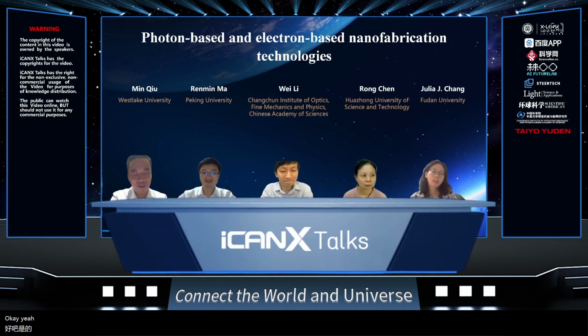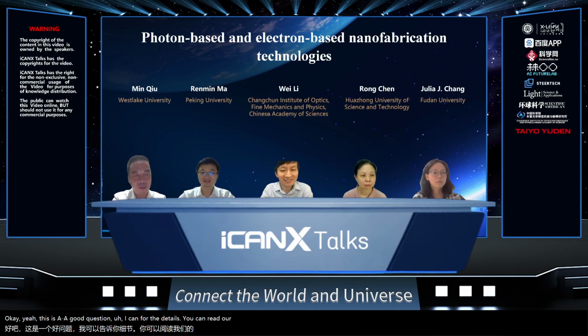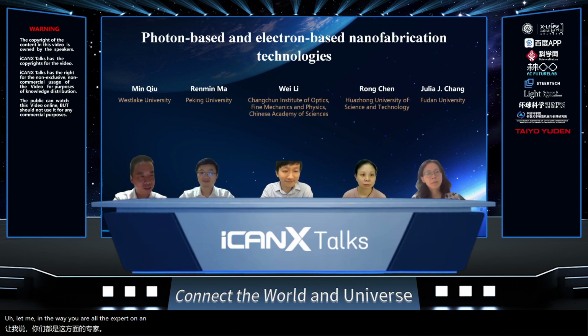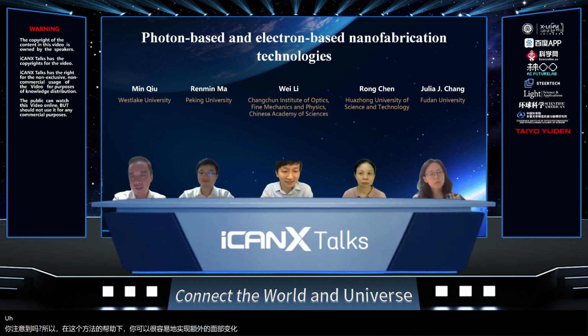Okay, yeah, this is a good question. For the details, you can read our arXiv paper, but I can explain this in a very simple way. Actually, this material is a lossy dielectric material sandwiched with metal devices. So it's a lossy material. And the loss will give you extra phase change when the light propagates in the films. And Renmin, Li Wei, you are all experts on this, so you know this. So with the help of this extra phase change, you can easily achieve the phase required for the color change, for the resonance, basically.